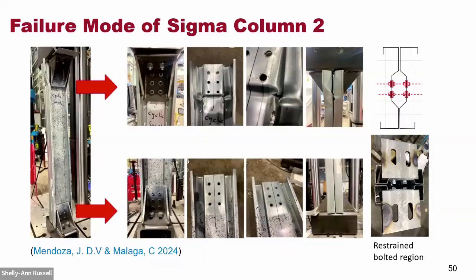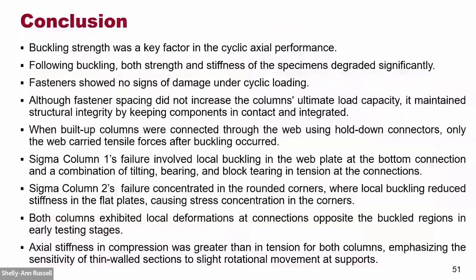For the second sigma column, we made changes based on the experience of Mendoza and Malaga. They said we should change the protocol, and they also changed the fastener connections. They applied a restrained bolted region at the bottom and top and tested these specimens, and you can see localized buckling again happened at the connection parts, as you can see from this picture.